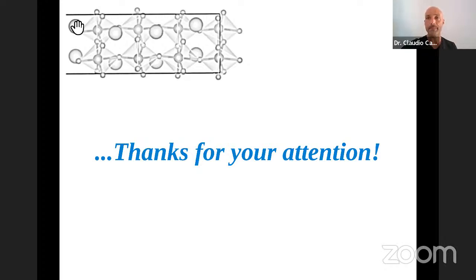Yeah. We have another question from Joe Briscoe. Is the shift in band positions related just to the strain, or is it also related to a voltage developed with the strain? Well, of course. Okay, so in our simple electrostatic model, our screening has been based on the simple assumption that the band alignments change with uniaxial strain was only due to electrostatic causes, so to the internal electric field that develops in the material.